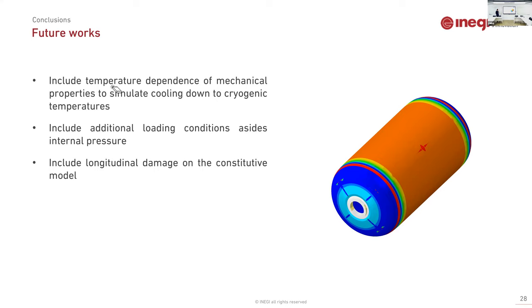When I do the curing simulation, for example, only the curing part, let's say it's a hypothesis that the yielding stress will always be higher than the applied stress, or in other words, the material will not yield, because if it yields, the model does not work, or it's not a natural way. I don't know if we may expect that. Let's say I have the yielding model active, but the development of the residual stress is always inside the yielding envelope. It never reaches the yielding or the failure strength. Ah, okay.